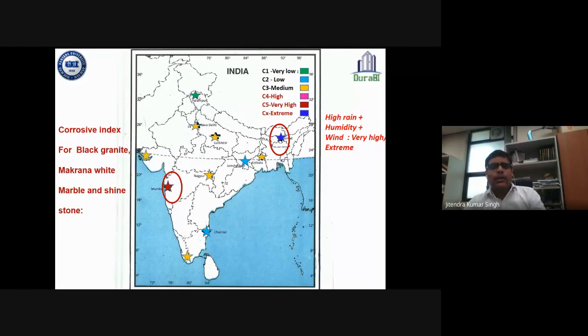We have also exposed black granite, marble, and sandstone. Here you can see that at Palanpur as well, there is no corrosion. But New Delhi, Lucknow, Kolkata, Nagpur, and Bhavnagar show a medium corrosion rate for the black granite, Makrana, and the sandstone. But in the case of Mumbai, you can see it's a seashore, and here the corrosion is very high. But in Chennai, the corrosion rate is low.